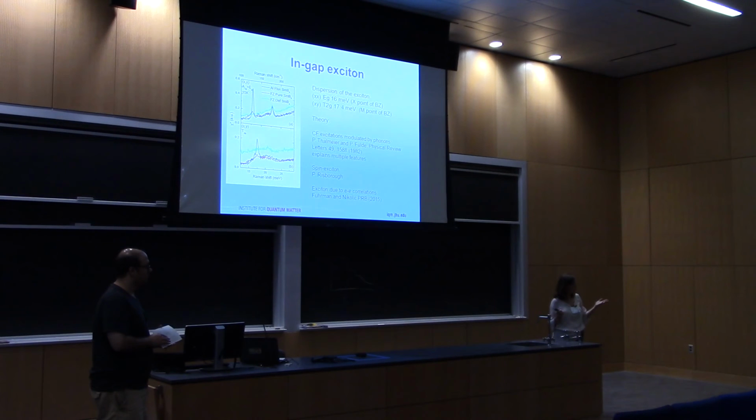You can also think about it as, because of disorder, we start to see all the local vibrations. This is why I wasn't sure about calling it longitudinal or acoustic phonon. In the latter case, I wouldn't think of it as a propagating one. Probably the correct way to look at it is just local vibrations of samarium within the places where there is a samarium vacancy.